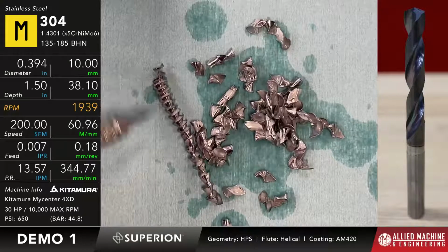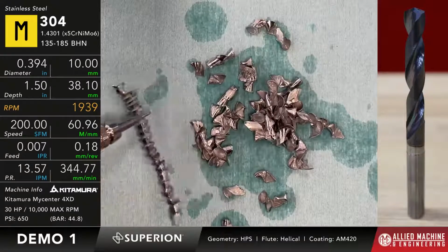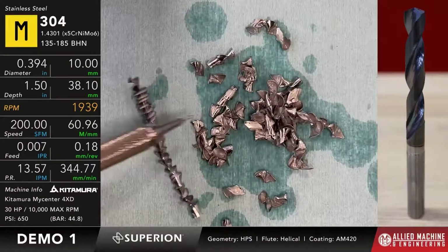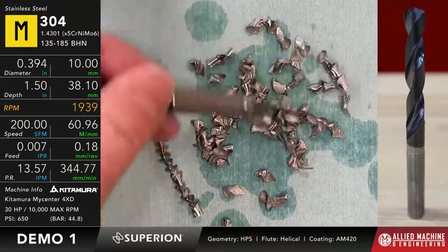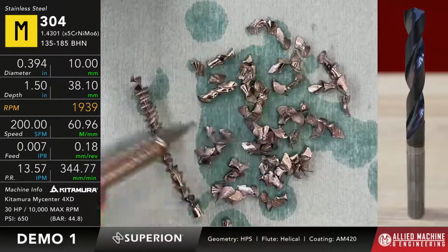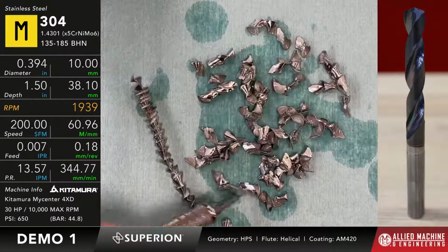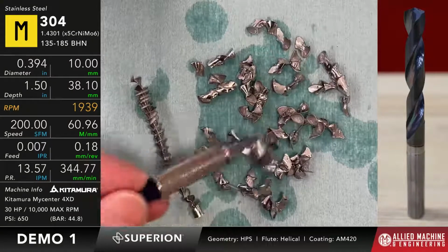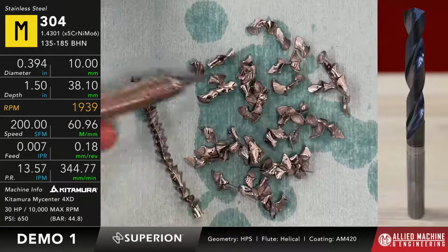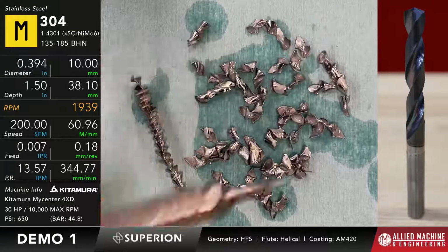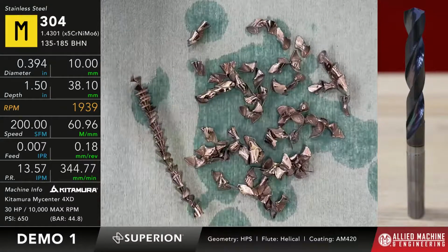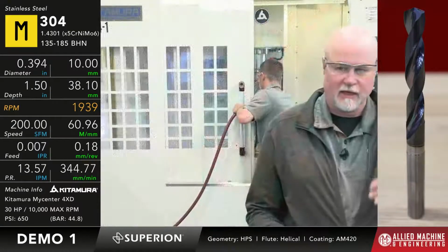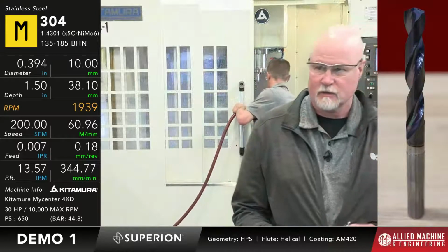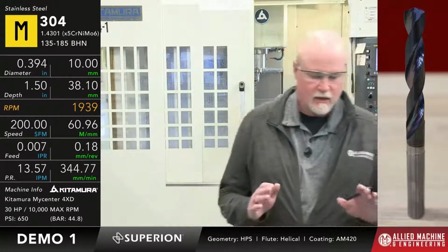So you can see that entry stringer, and once again, since the material is fairly elastic, you're going to get that. But if you look at the rest of the chips that we made, the rest of the chip form is quite good. And as we know, 304 stainless can be a little bit finicky at some point in time. This made a nice little small chip. It evacuated real nice. The spindle load was even from the beginning of the cut to the end of the cut, which is the way that we want it to be. So that was pretty good, I think.